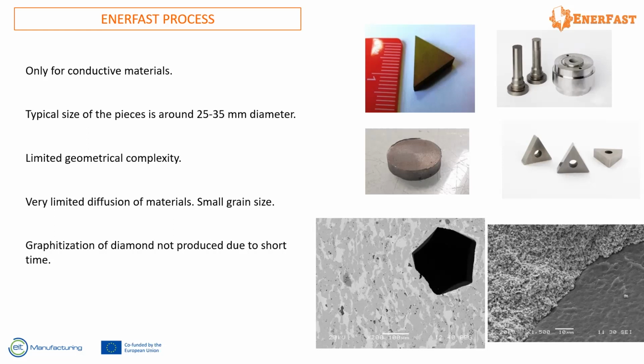The size of the pieces: as we are using very high currents, there is a technical limitation about the maximum current you can put in a die like this. The sizes we are playing with right now are between 25 and 35 millimeters in diameter, if we think about a single cylinder sample, and we are trying to increase this size. There is also limited geometrical complexity. We can do triangles, rectangles, but if we are thinking about, for example, additive manufacturing, very complex shapes, this is not the easiest way to do complex shapes.